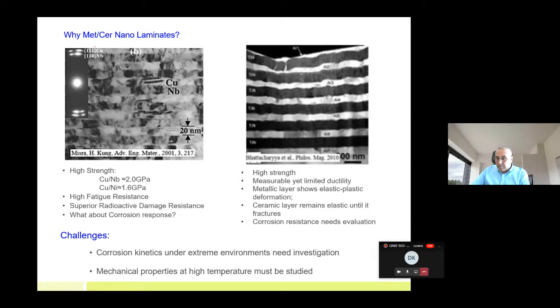So mechanical properties certainly can be improved, and metals tend to have a lot of ductility, so that addresses some of the problems that we've seen in the thin films. And they give you all sorts of advantages: fatigue resistance, radiation resistance. However, the problem is corrosion. If you're going to use it in the oil and gas industry, if you put a copper niobium together or a bimetallic couple, that's a recipe for disaster. You will have galvanic corrosion. You cannot do that.